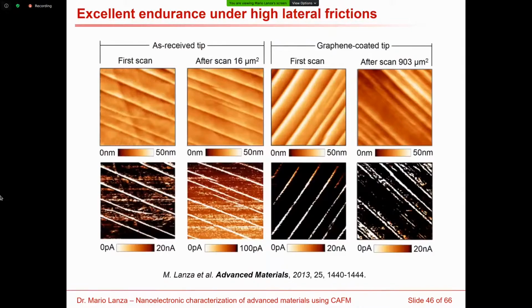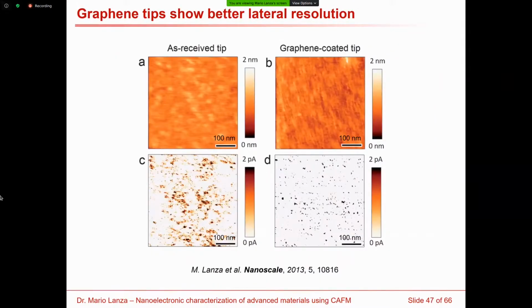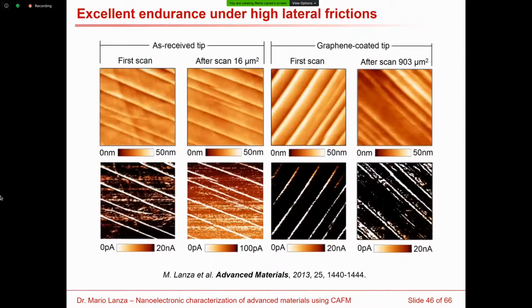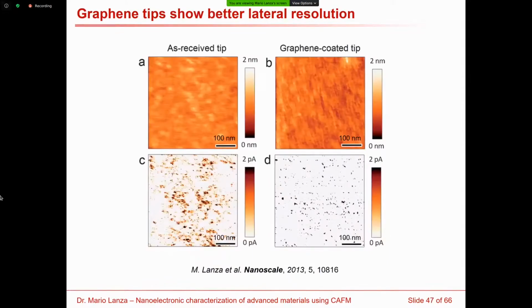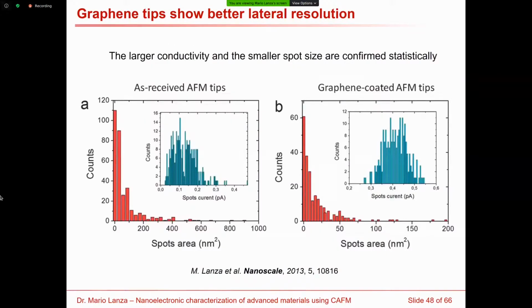We scanned different samples, we did IV curves, we did current maps, and we also always observed that the graphene-coated tips live much longer. We analyzed these scans that you see in the previous slide. This slide is for copper substrates, and these ones are for high-K dielectrics. You can see that here the current map that is collected with the graphene-coated tip looks with much better resolution, and that the currents measured are higher. And the size of the spots is smaller, which means also better definition of these defects that are contained in the dielectric.